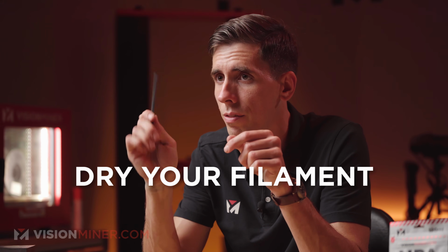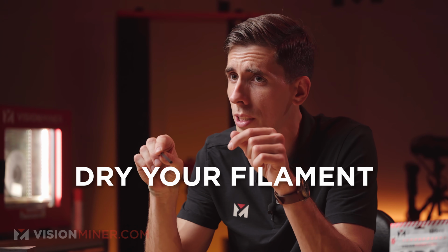It is definitely a little bit stiffer than the Onyx that I've felt in a lot of situations. Just make sure you're drying the filament because it is very hygroscopic, and if you don't dry it properly, your parts are going to bubble, ooze, and cause delamination or just poor surface finish. But when you've dried it and tuned it in, it prints like an absolute dream.